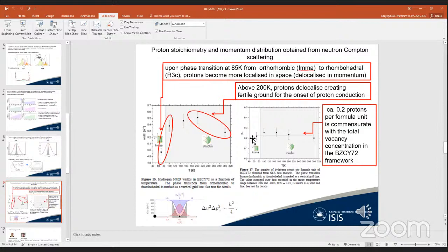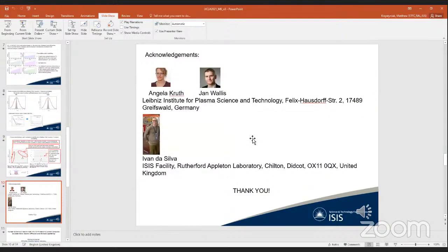And also by measuring the width of proton momentum distribution as a function of temperature, we can see that across the phase transition, protons become more localized in space and delocalized in momentum, and above 200 K protons become delocalized, creating quite a fertile ground for the onset of proton conduction at higher temperatures.